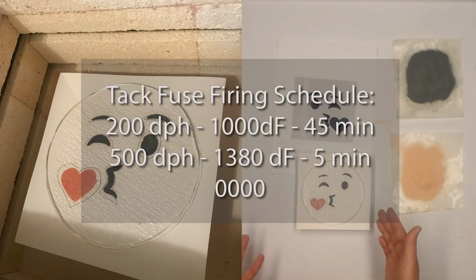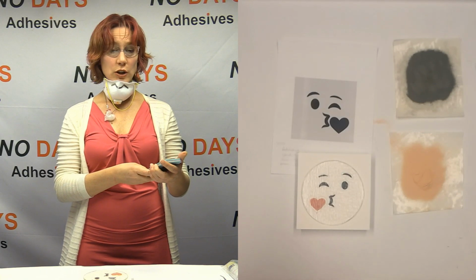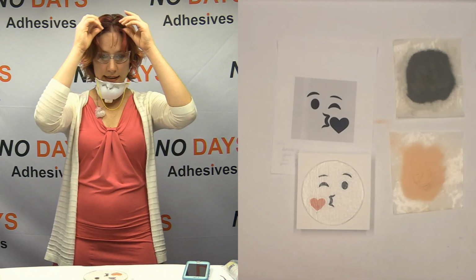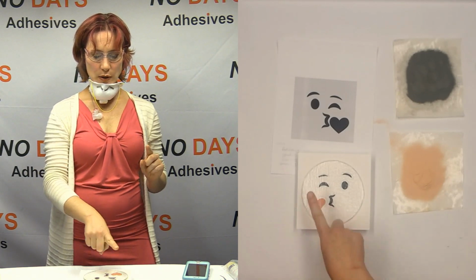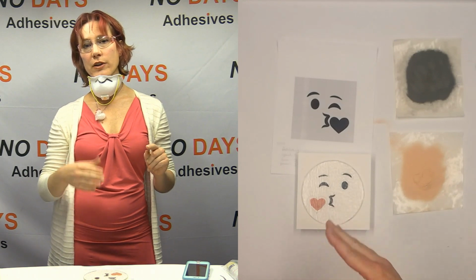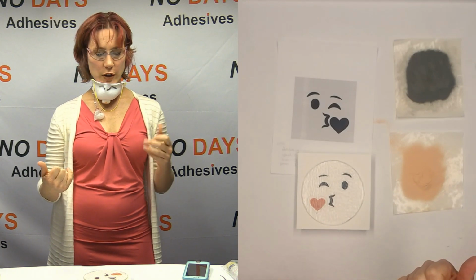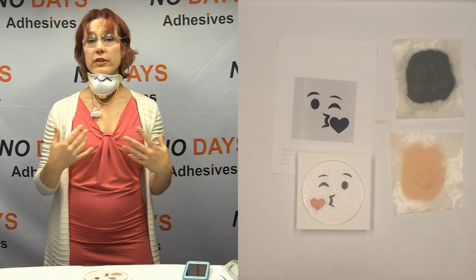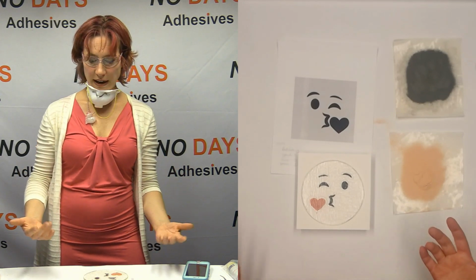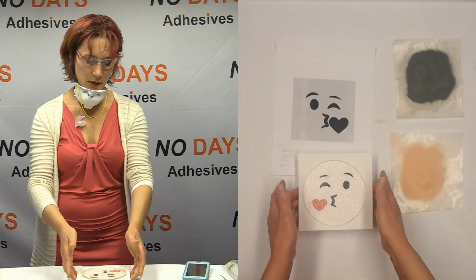My firing schedule on this: 200 degrees an hour to 1000 degrees, and then I held that for 45 minutes. And then I went 500 degrees an hour to 1380 degrees, and then I held that for 5 minutes, and then I just turned it off. Now, that seems like a long, slow first firing, and it is. What I'm doing is I'm slowly heating the powder wafer material up until the binders in there burn off. You could probably go faster if you wanted to. I just found that this schedule works for me, and I haven't had to go any faster, so if it works, I continue to use it, right?